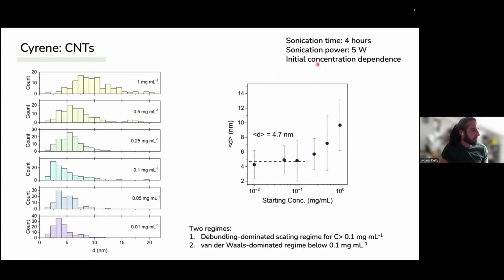Then we did the same thing for an initial concentration dependence. We held the sonication time constant at 4 hours. Again, we used a 5-watt sonication power. And then we varied the concentration from 1 mg per mL down to 0.01 mg per mL. What we find is, again, a wide distribution at 1 mg per mL, and the diameters start to move to the left. So there's clearly some sort of change in diameter, where it becomes constant below 0.1 mg per mL at about exactly the same value as we found for the sonication time dependence.